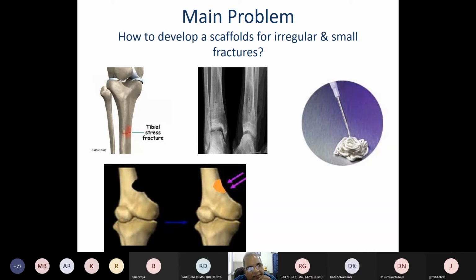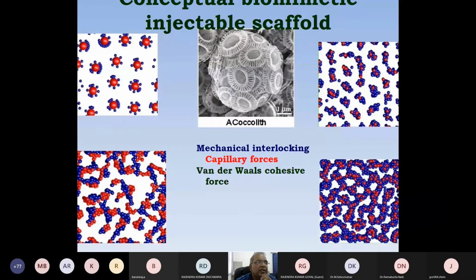Once you inject it at that particular site of the defect, it undergoes cementation, and cementation is an exothermic process. So once it goes through cementation to fill the gap, it increases the nearby temperature, and that creates problems for the cells in the vicinity of the defect. So it creates some irritation and other health issues. So people thought of developing another product which is free from cementing action. There were some companies in India that produced it, but the problem was that as they injected it into the body, under any physiological condition where water or body fluid was present, the structure was not stable. It was getting washed away.